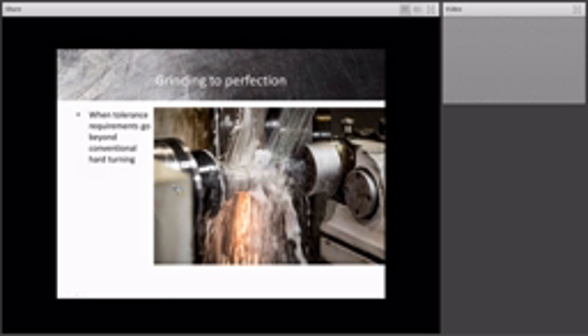Now, beyond that, the same component is then taken to a grinding operation, usually a cylindrical grinder, an external cylindrical grinder, that's with a customized wheel that's designed to hit 3 surfaces at once on this component. And the objective with this component is then to take that and grind the OD to ensure that you've got perfect roundness with a very tight tolerance, less than 8/10,000ths of an inch on those diameters. And when the requirements do go beyond those things that you can achieve with turning, grinding may be an option, and it certainly gives a nice finish.